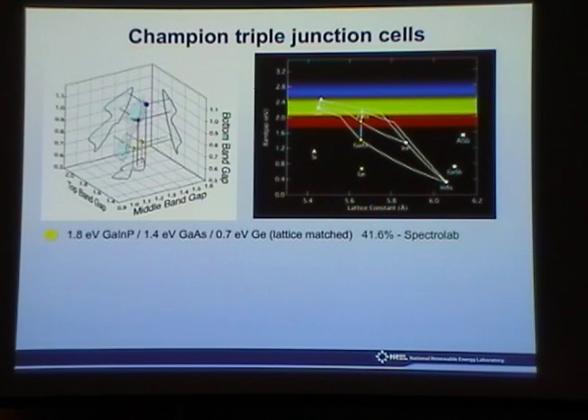Part of it is that it's hard to acquire that evidence because you develop an optical system to put outside. It's got a fixed geometrical concentration. So to actually go about installing a system that was at 100x, then 400x, then 1000x, you really need to develop three totally different systems. We've done some laboratory-based stuff with lasers on single junctions. They don't show a lot of degradation rate variability between intensities, but it's small statistics.